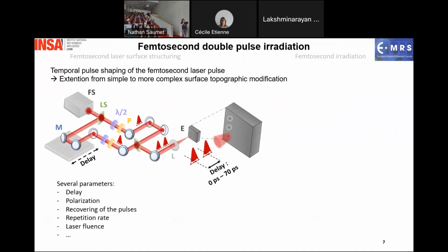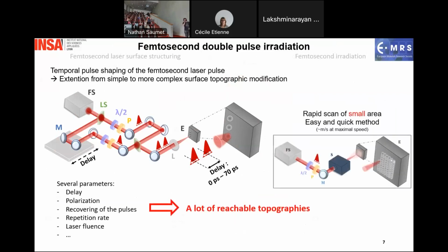We have a lot of parameters. The delay, also a half-wave plate and polarizer to control the polarization direction of each pulse, the repetition rate, laser fluence, etc. All these parameters permit a lot of reachable topographies, and when we want large surfaces, we can also use a scanner with moving mirrors. It's a very fast method because we can have a beam speed at the surface of meters per second, which permits making very large surfaces in a very short amount of time.